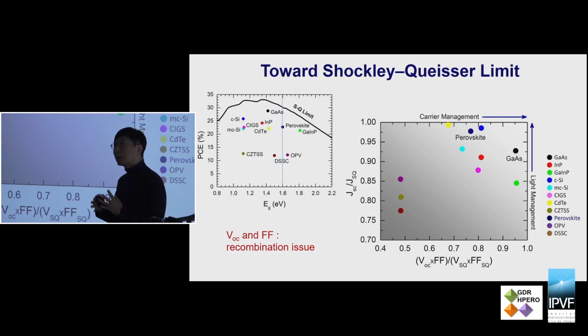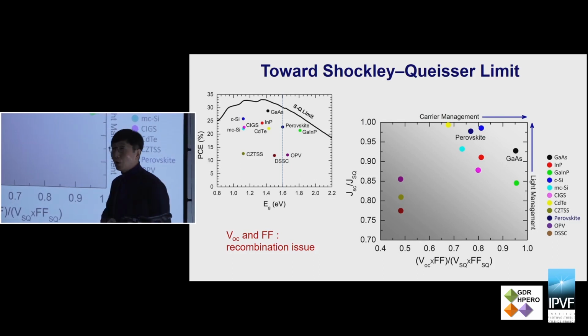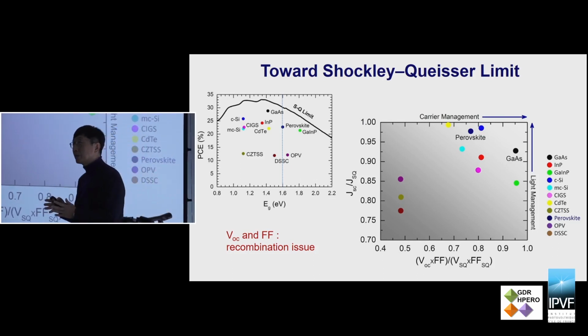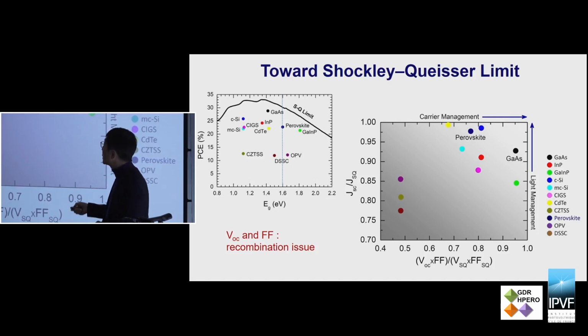So the research direction in gallium arsenide, I'm not an expert in gallium arsenide, but they would like to increase the short circuit photocurrent density, for instance with the photon recycling method or something like that. How about the perovskite? For perovskite, the short circuit current is very close to the theoretical value. However, there is a large gap between the observed value and the theoretical value in terms of open circuit voltage and fill factor. So we have to increase the open circuit voltage and fill factor to reach the theoretical efficiency, such as 30% from a single junction using the perovskite material.